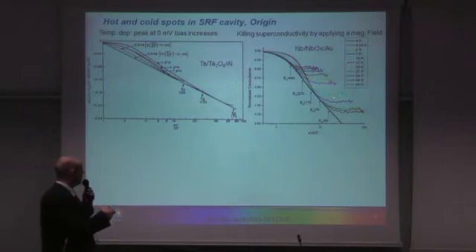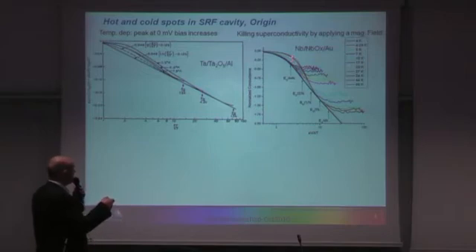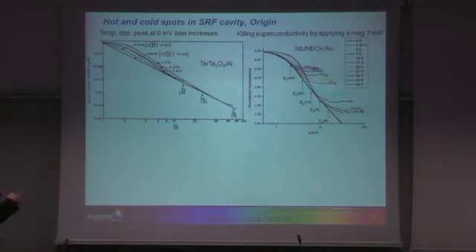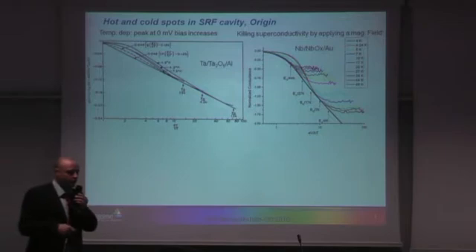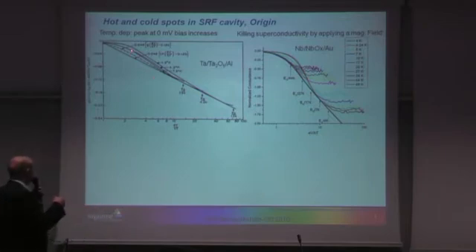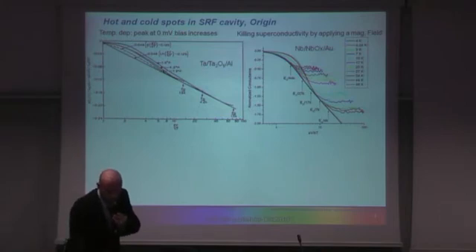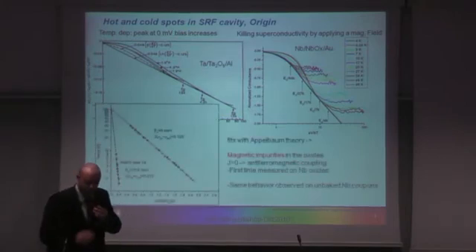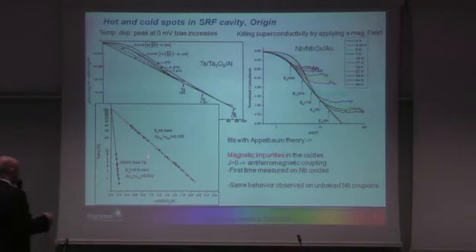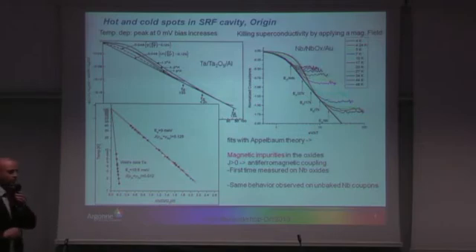The fit is very good above 7K, but below 7K it fits less well at low voltage. Weides observed the same behavior — it fits well at high bias and high temperature, but his experiments are slightly off from the theory at low bias. The temperature dependence of the amplitude of this peak fits quite well with the Appelbaum theory for three different junctions, all falling on the same line.